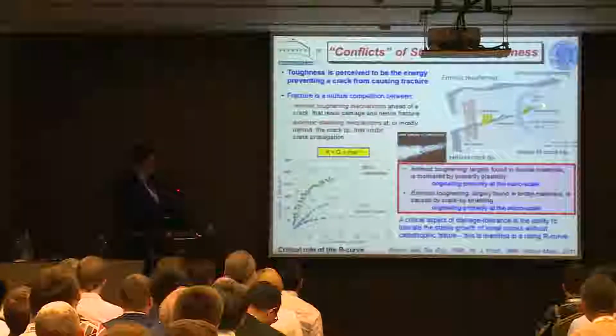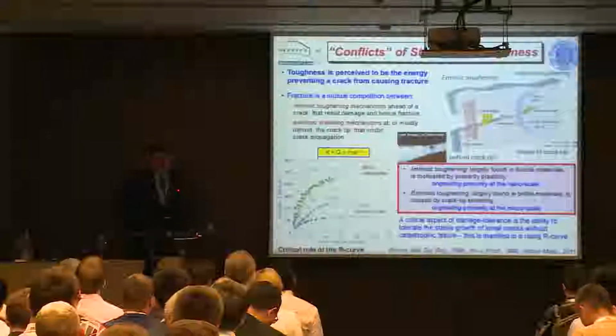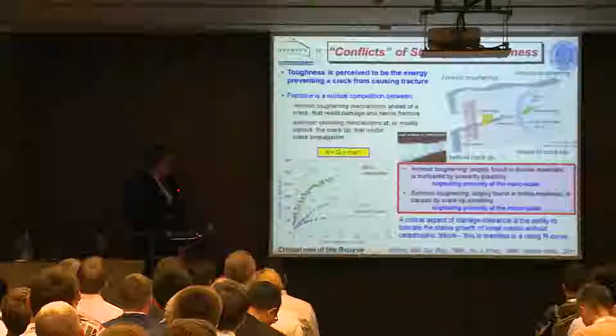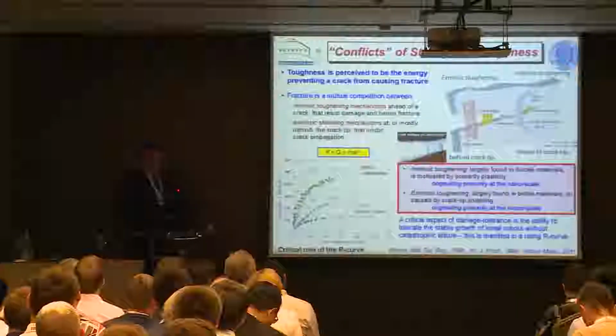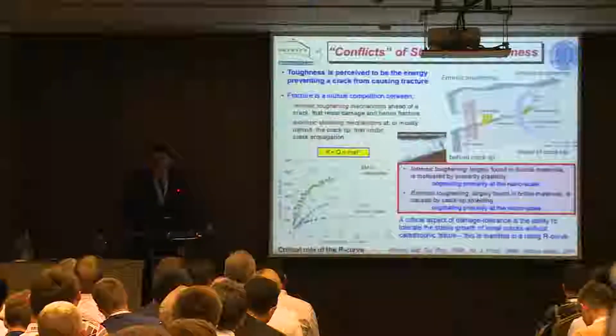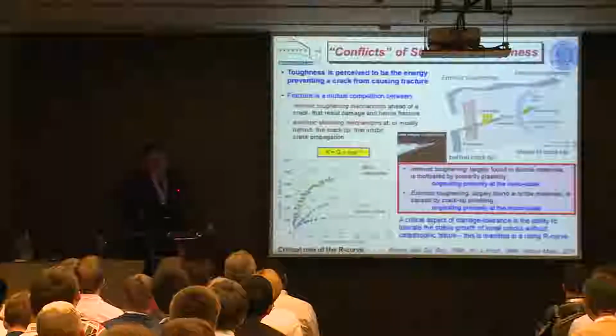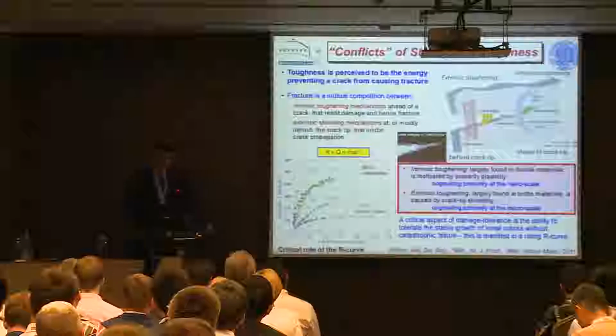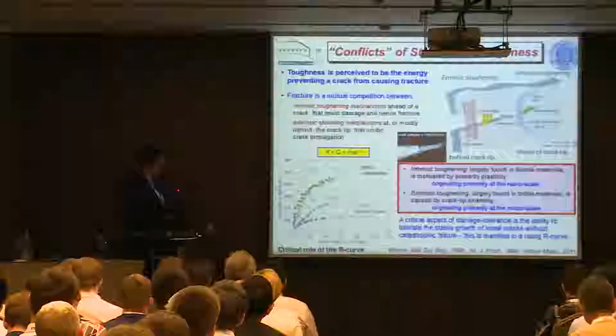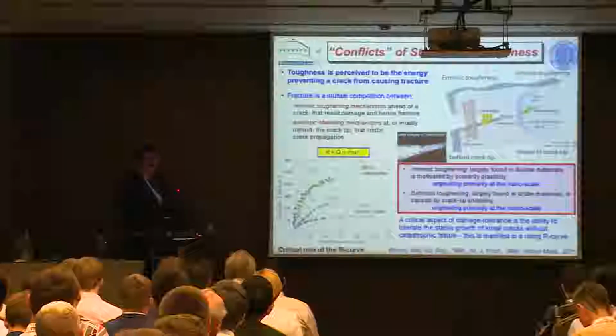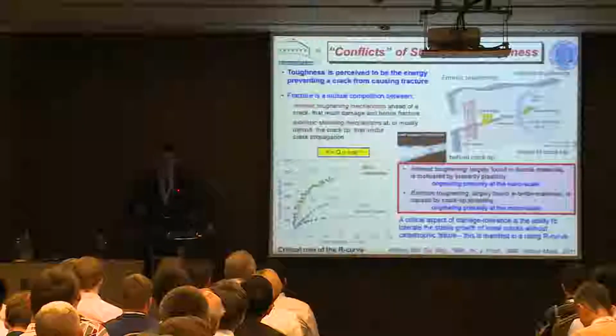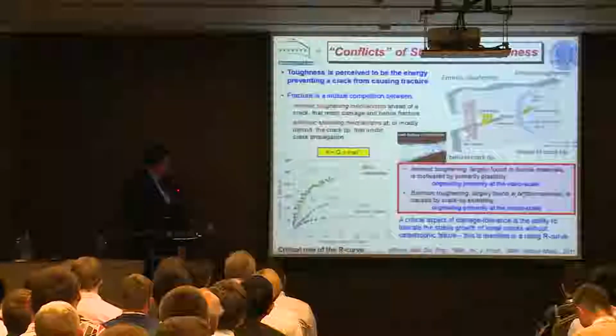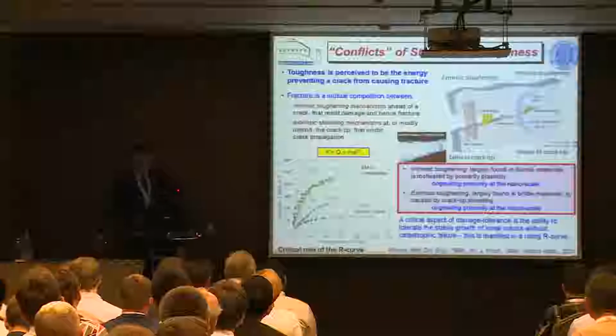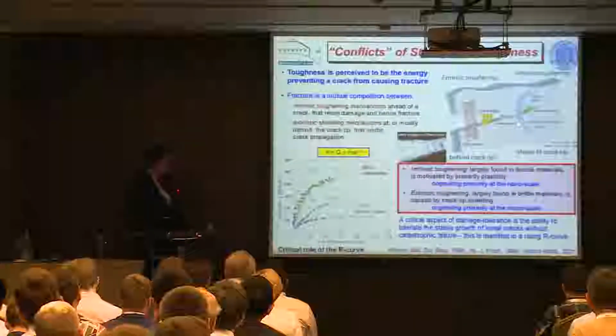And then there's another class of mechanisms that operate behind the crack tip or at the crack tip. And I call these extrinsic mechanisms, and these are not associated with plasticity necessarily. They're associated with shielding, and they effectively lower the local stress or strain field at the crack tip compared to what you think you have. And there's a number of mechanisms. Bridging is one, of course, as we see in fiber composites and lots of different materials. Crack closure, which is a wedging mechanism, is seen in fatigue, and deflection.